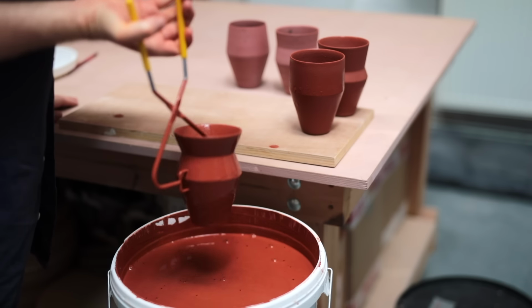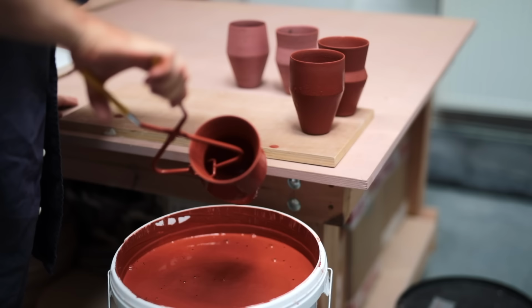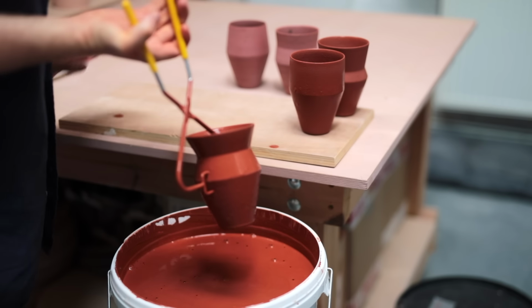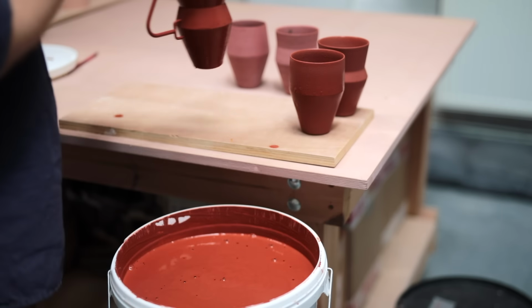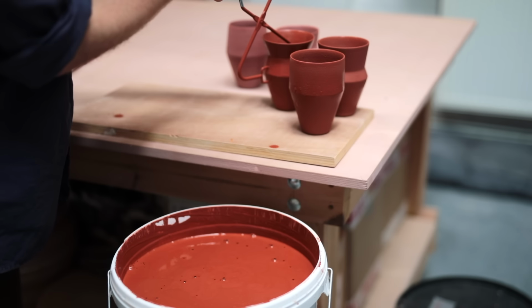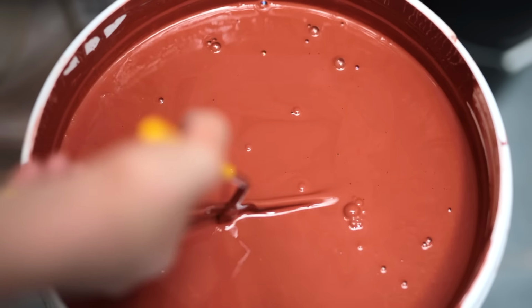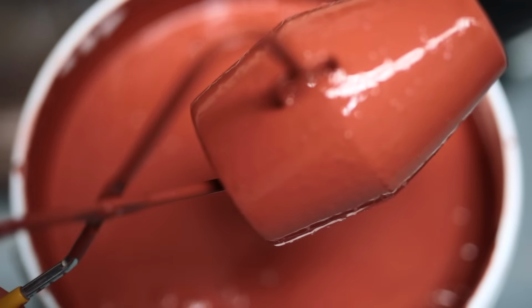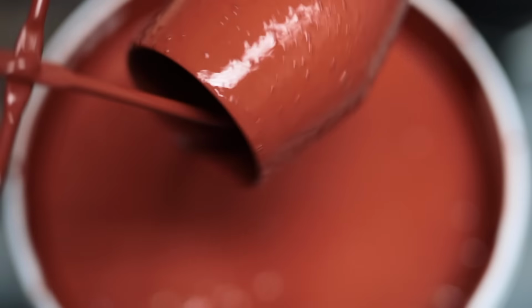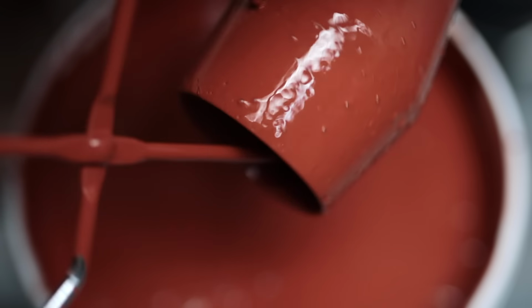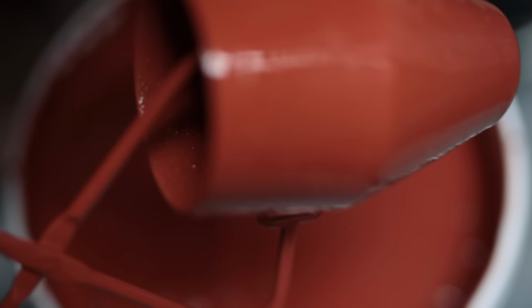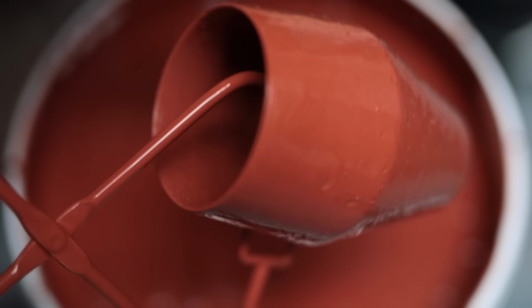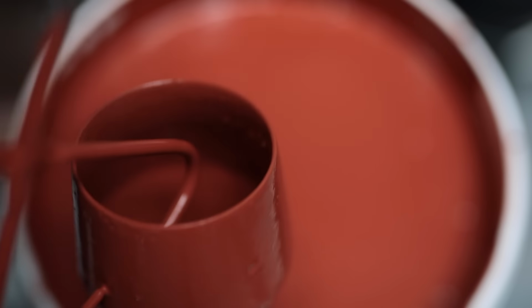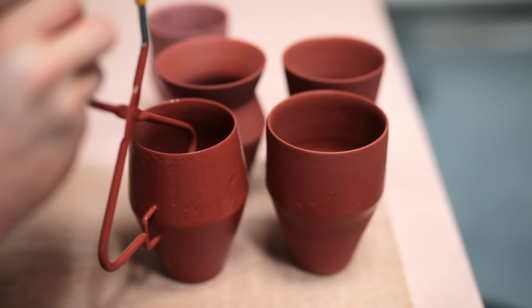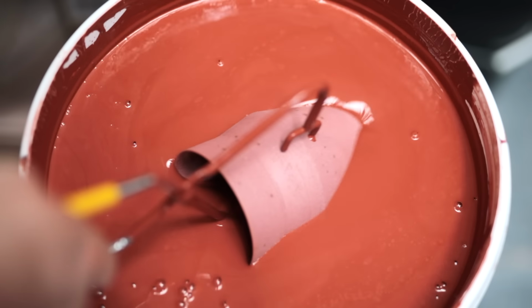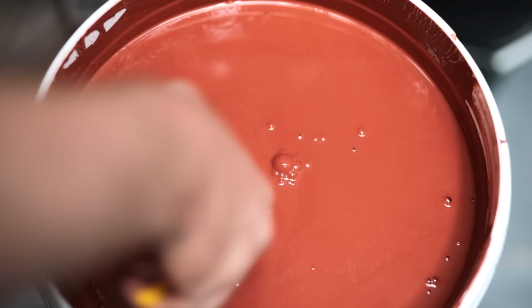Equally, if you dip it for too short a time, you can end up with a layer of glaze that's too thin, which most of the time results in a surface that's nothing like what you intended. So you do sort of have to find the sweet spot for your particular pots. And in this instance, as I'd never used this glaze on this scale before, this really was just a shot in the dark. This could be too thin, or it could be too thick. I'll have no way of knowing until I've fired them. The reason I'm blowing on the surface is that it pops all the tiny bubbles that appear as the glaze sinks into all those minute holes left over from where grog was torn out of them.